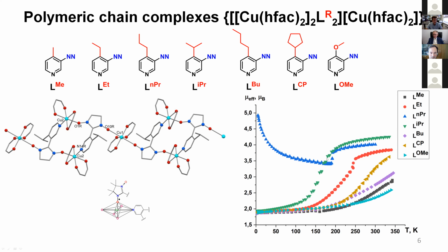After doubling of the cell, the copper-nitroxide distances in dimers change dramatically. In one, it even increases, and in the other, it reduces. In the second dimer, the character of exchange interaction changes from ferromagnetic to antiferromagnetic, which causes a sharp drop in magnetic moment near 200 Kelvin. Below this temperature, an increase of magnetic moment is associated with restoration of ferromagnetic exchange interaction in the first dimer due to the significant copper-oxygen of nitroxide distances.